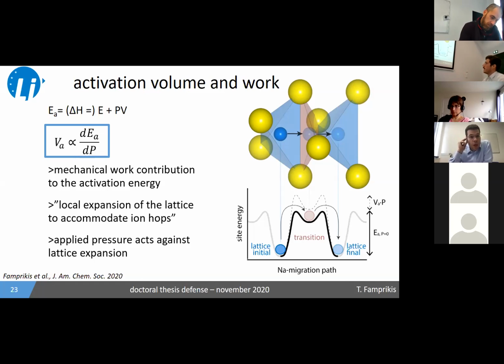You mentioned a Grüneisen parameter. For me, a Grüneisen parameter is a factor of anharmonicity. Right? We usually draw these harmonic potential wells. Ionic jumps must be intrinsically anharmonic. So how does the anharmonicity come into play here in the activation volume? Or how can I envision or visualize the fact that there's some anharmonic contribution when it comes to this derivation of the activation volume?